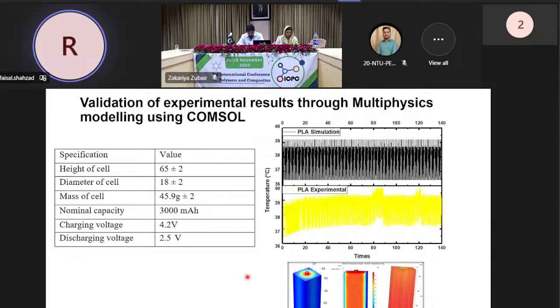So you can see this simulation data is almost close to our experimental data. We have done all the data from 0 to 140 hours, and you can see the simulations, the CFD of the battery thermal - it's a single cell, so we've done single cell simulations.